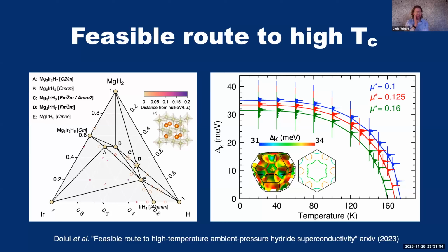Now, these calculations are extremely sensitive. It turns out that when you do an optimizing search for superconductors, you optimize for materials that are just very perfectly aligned to have maximal properties. And in this case, it's got a very high and peaky density of states near the Fermi surface, which means the calculations are rather difficult to converge in terms of k-point grids and so on. This gives some of the challenge of coming up with a definitive Tc.